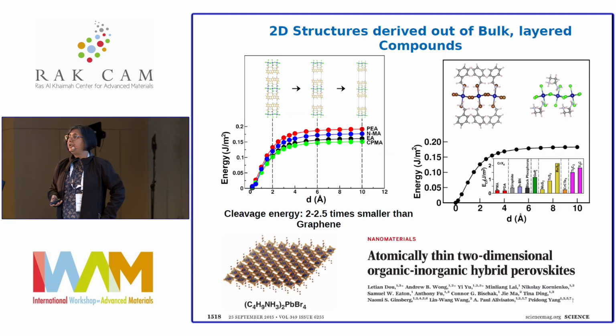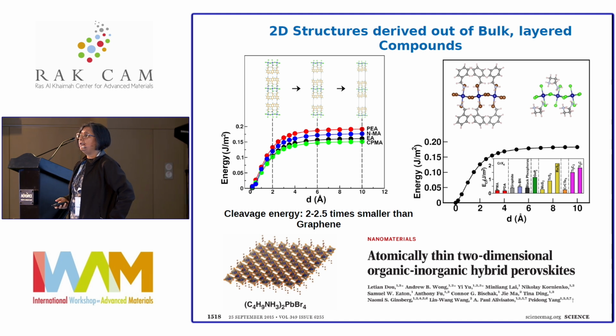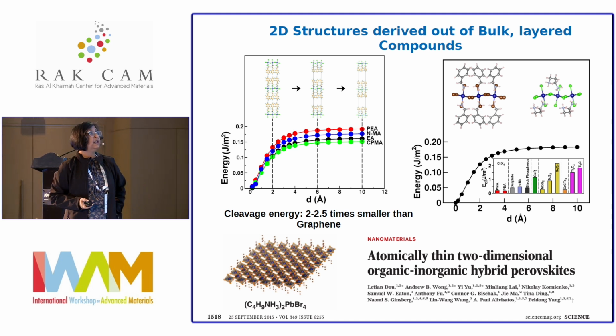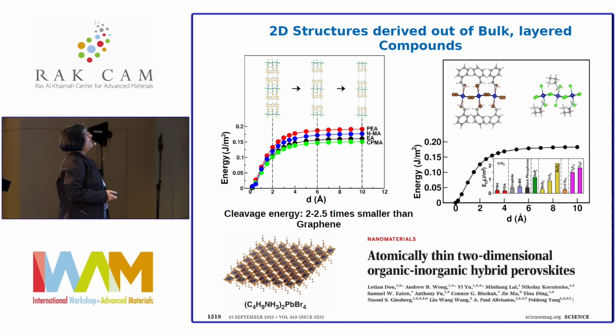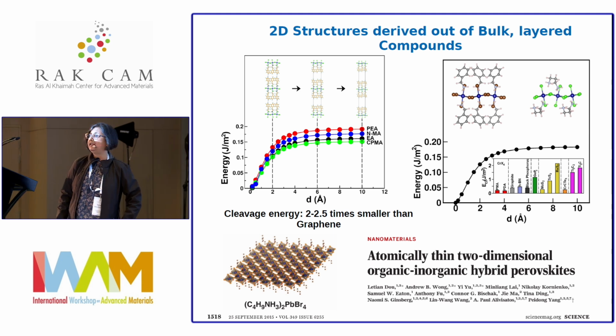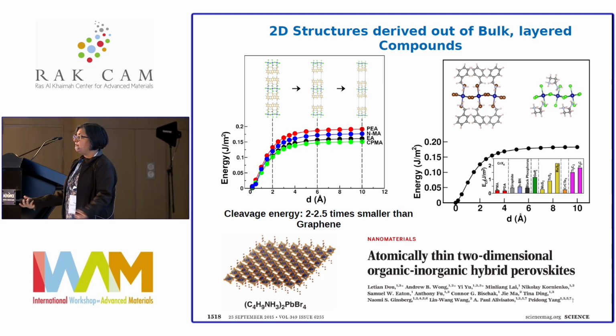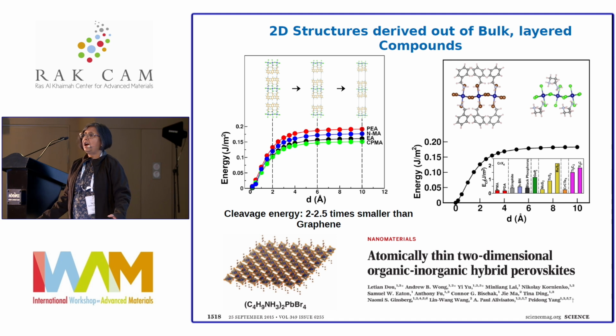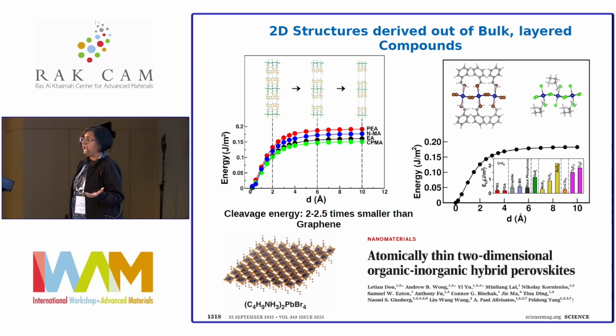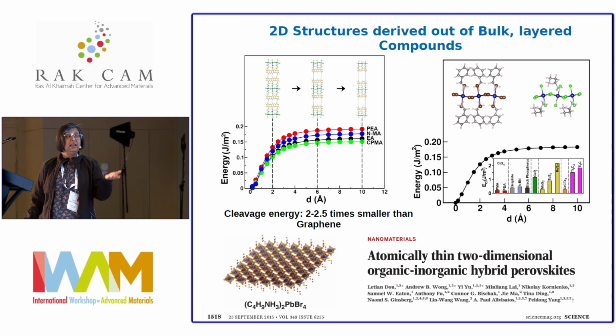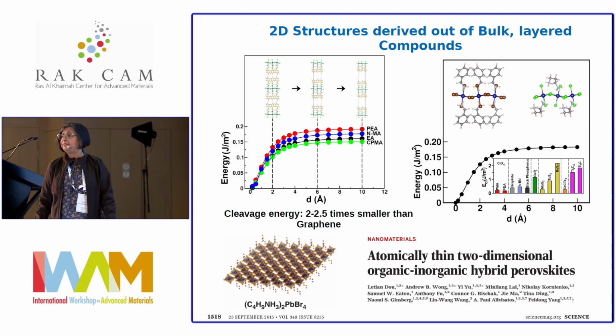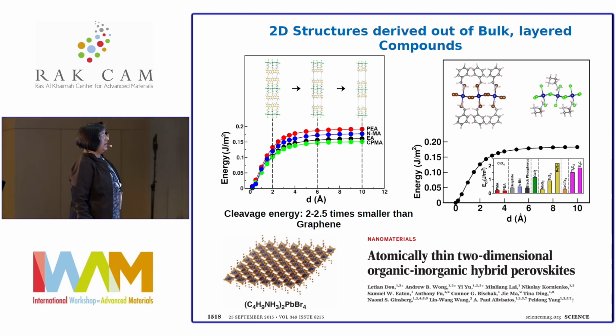Now, can you make 2D structures out of this? For that purpose we calculated the cleavage energy. And we found that the cleavage energy, which is shown here, is 2 to 2.5 times smaller than that of graphene. So if you can make a 2D structure out of graphite, making graphene just by the Scotch tape method, that should be possible also for these hybrid organic materials.